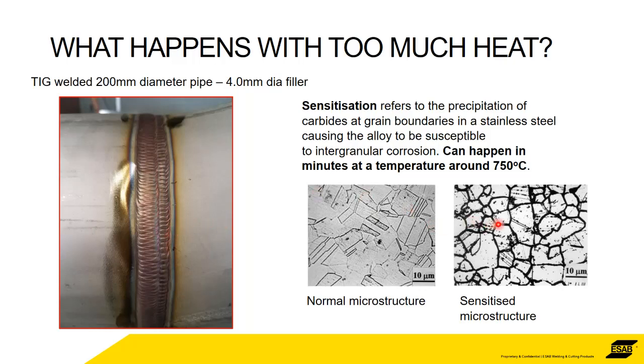So much so that we had what's called sensitization. So basically, you get a precipitation of carbides at grain boundaries. So essentially, you're robbing the stainless properties of the steel. It's got sensitized, so it's not stainless steel. Essentially, in a nutshell, it's not stainless steel, so it rotted. And on the face of it, it looks a good weld. You'd be pleased. Well, I'd be pleased with it.